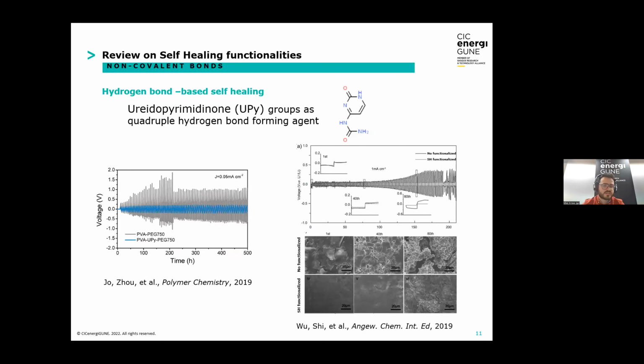If we move to the electrochemical performance, this self-healing allows an increase in the cycle life of the battery with these polymer electrolytes. On the left-hand side figure, we can see lithium stripping and plating with self-healing functionalized electrolytes in blue, and non-self-healing electrolytes in gray. The lithium stripping and plating overpotential is much lower in the self-healing functionalized material. But of particular interest are the scanning electron microscopy images, which confirm how homogeneous interfaces can be achieved by incorporating these self-healing functionalities. On the top row we can see the lithium metal surface with the non-functionalized material, and on the bottom row we can see how much more homogeneous the lithium surface is after the lithium stripping and plating process.